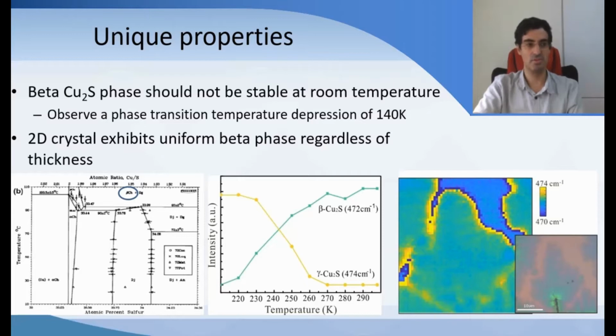equilibrium conditions. So also we see that this is not epitaxial, so it's not a quenching effect, and it's not an interface strain effect, because no matter how thick your Cu2S is, we always see it forming the beta phase. And so this is interesting because we really don't understand what makes it stabilize in that normally unexpected thermodynamic phase. The other thing is that beta Cu2S might be more interesting than gamma Cu2S because it should have superionic conduction, and it also might allow us to use the phase change for, let's say, memory.